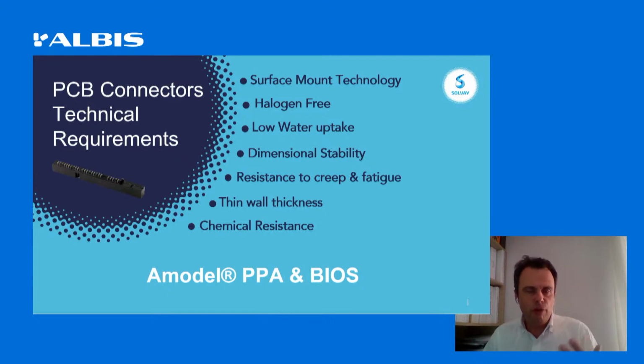It needs to be halogen-free to avoid electrocorrosion. It needs to have a low water uptake to first avoid corrosion, and second, guarantee a certain level of dimensional stability. You need to resist creep and fatigue, to have eventually thin wall thickness, or ideally thin wall thickness, and I will also explain why, and potentially need to be chemical resistant. The obvious answer to these requirements are PPA, and in our case it's Amodel PPA and Amodel PPA BIOS.